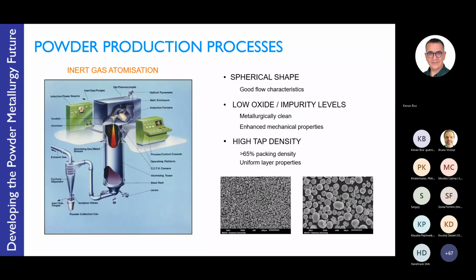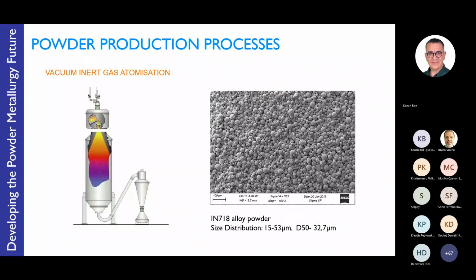So moving on from inert gas atomization, the premium process is the vacuum inert gas atomizing facility. So a similar configuration, but in this case the melting process is completed, often top pouring again into a tundish, using a hermetically sealed chamber, where the various alloys can be trimmed and samples taken, but certainly is a very efficient and clean process metallurgically when it comes to the melting process. Because it's done under vacuum, that does produce much less oxidation of the melt, and that in part improves performance.